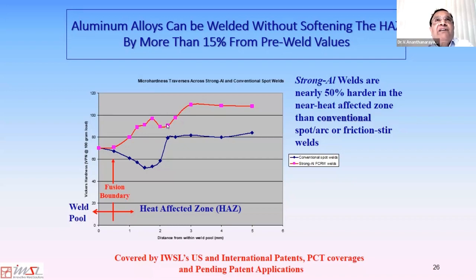The second part of it is most of the outer surfaces of a mash seam weld consist of wrought material microstructure. The outer surfaces are not melted together, are not melted during this welding because they are in contact with water-cooled copper alloy welding wheels. And since they are not melted, they retain the wrought microstructure and the corrosion resistance of the wrought metal itself. So these two are very attractive for boat manufacturers. There are a good number of aluminum boat manufacturers in the Detroit area and also aluminum shipbuilders in the United States for the US Navy. I'm working to, and also automotive body panel builders in the Detroit area. I'm trying to do the mash seam welding for these applications.